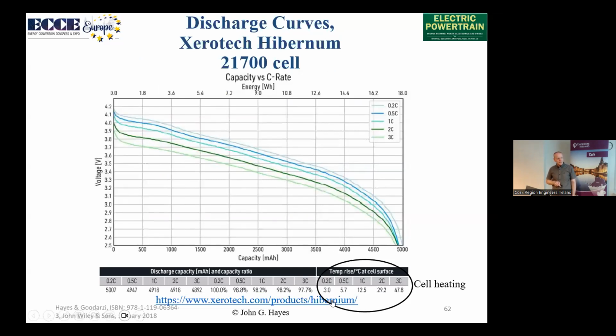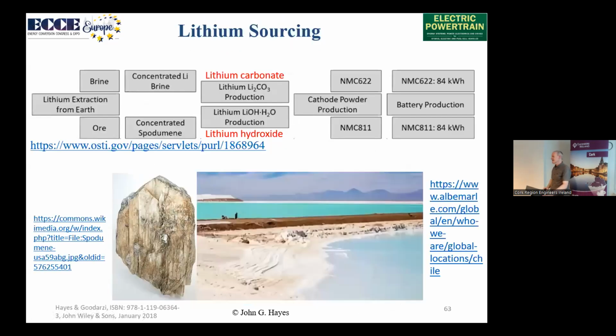When I was doing a 3C discharge of this pack, so this is, say, a 5 amp pack, if I pull 15 amps out of this cell, the temperature of that cell internally rose 50 degrees. So when I was at -20 or -30, in reality, within minutes, it eventually got up to a very high temperature. And that's why we see it there. As it seems like we're getting the full capacity, no matter what we do in terms of temperature or capacity. That's because the temperature of the pack is increasing, even if the ambient is very, very low. So we're almost there. Last couple of slides.